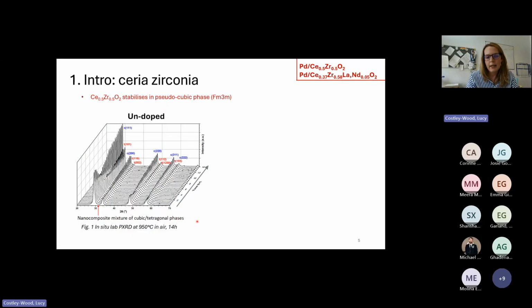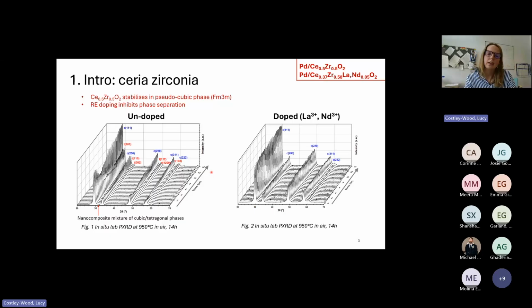You can see this by in situ powder diffraction over time at high temperature. Here this is 950 degrees. You get phase separation into a ceria-rich cubic phase and a zirconia-rich tetragonal phase. That is because these are the two different symmetry structures that ceria and zirconia would each stabilize into if they weren't mixed in a cubic phase. For this reason, most commercial formulations include rare earth dopants. In this material we're using, a Johnson Matthey commercial catalyst formulation, we have lanthanum and neodymium. Just the addition of really tiny amounts of these dopants can prevent the phase separation under the equivalent conditions.